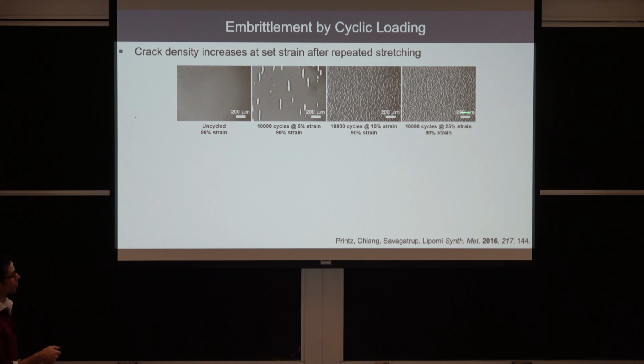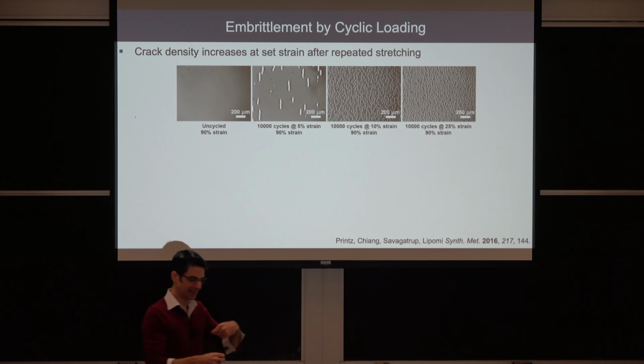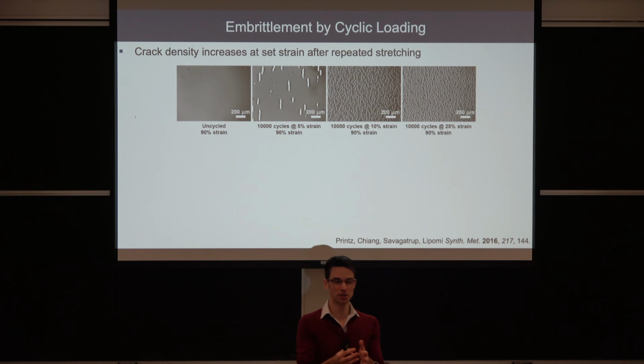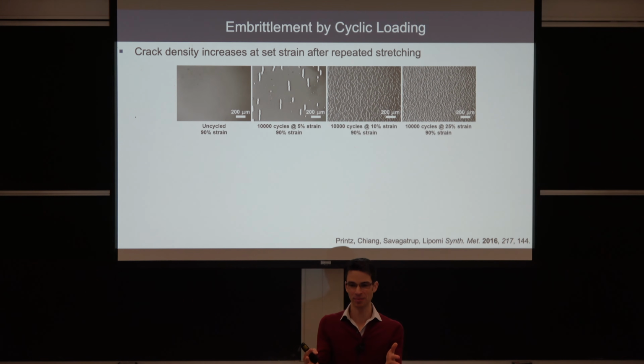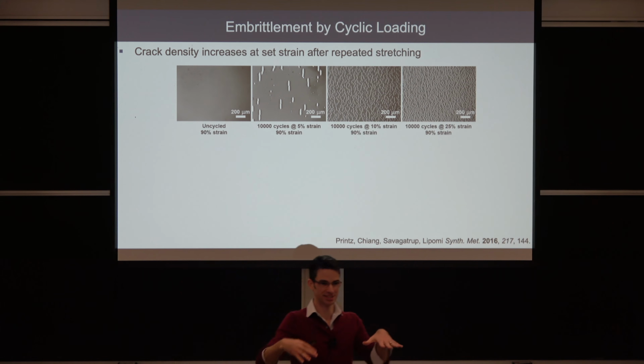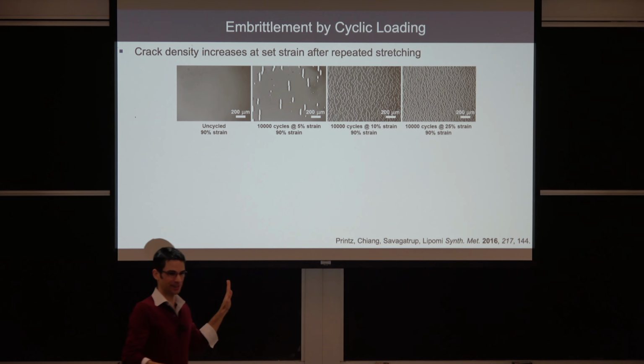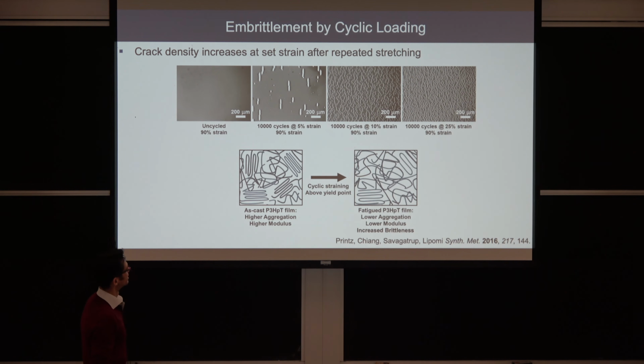So it also becomes more brittle. So it becomes less stiff but also more brittle. It becomes a little bit like the soup skin on Campbell's tomato soup after you leave it out for a few minutes, and you get this soft skin that's also brittle on the top surface of the soup. Same kind of material here. And here's our little cartoon. So this is the as-cast material and then the fatigued material. So it becomes basically like the top of a Tic Tac box after you bend it over and over again.